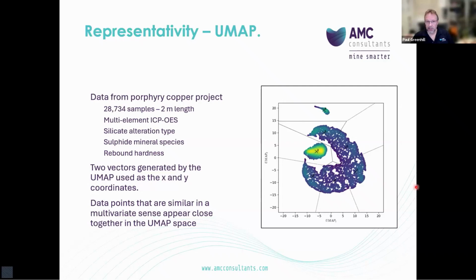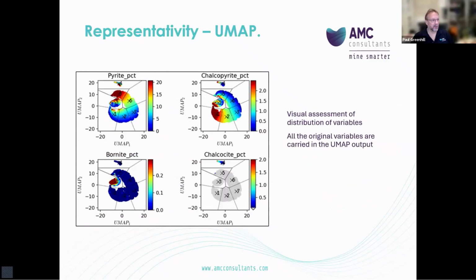So let's have a look at an example of where we've then used the additional data within the database and overlaid that on the UMAP. So this is a visual assessment of the distribution of some of those other variables. In this case, it's the sulfide mineral grades that have been plotted against the UMAP coordinates. So what we can see is the UMAP itself clearly separates samples with different sulfide species.